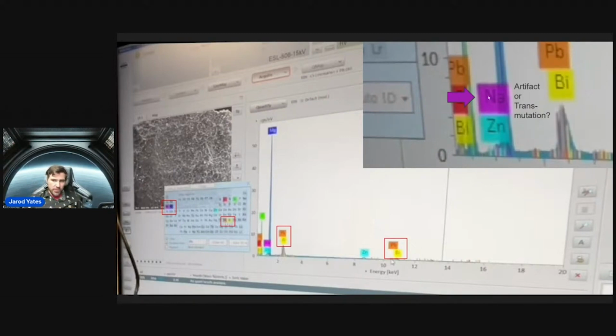The reason why this is important, that we saw sodium, potentially important, is because if this thing was in a really high energy environment, like a gamma radiative environment or a nuclear reactor type environment, any high energy radioactive environment, you might start seeing some transmutation of elements where heavier elements are being transmuted into lighter elements. So I'm just throwing this idea out there that the magnesium being transmuted into a few artifacts of sodium, or some of the presence of lead that we're seeing, maybe that could have been bismuth getting transmuted into lead. I'm just throwing that out there as an idea. Take it with a grain of salt.